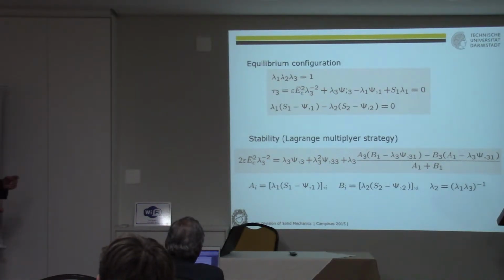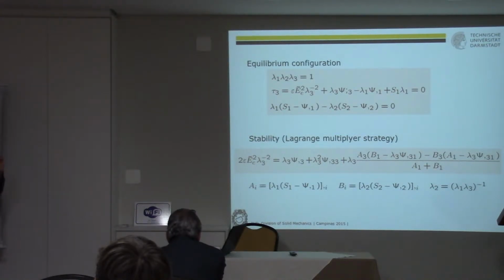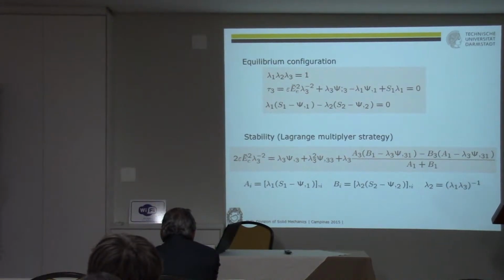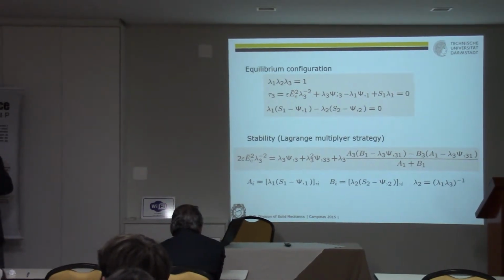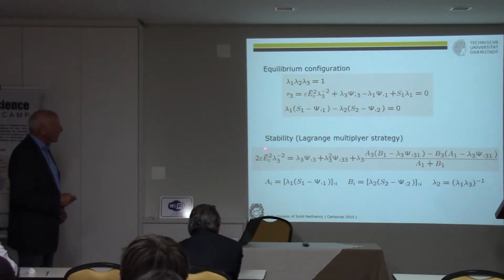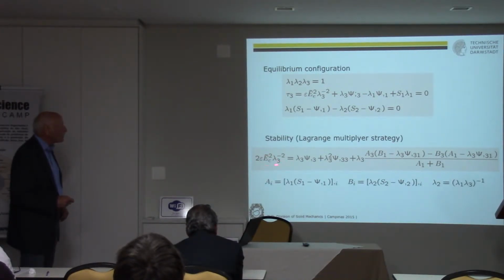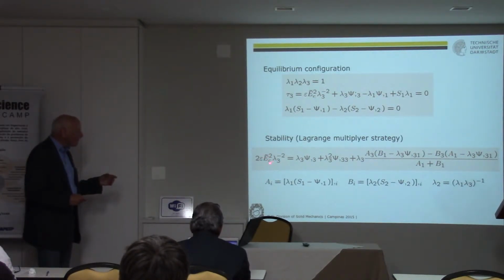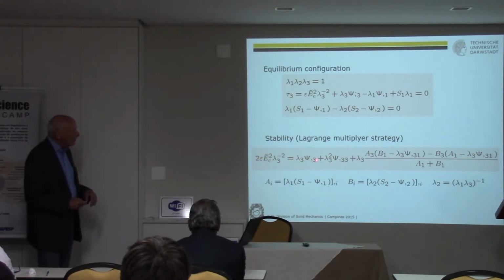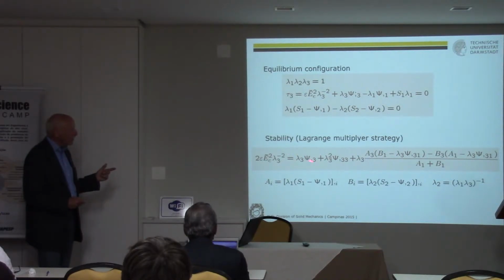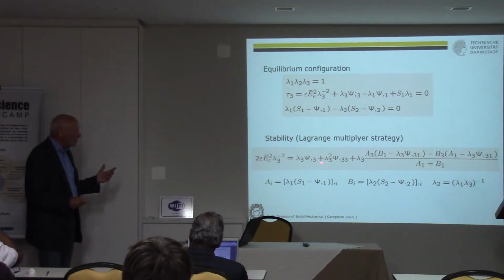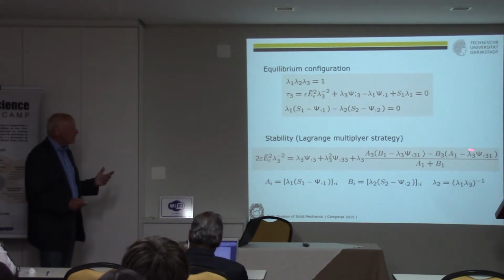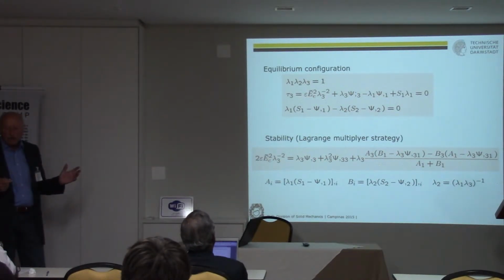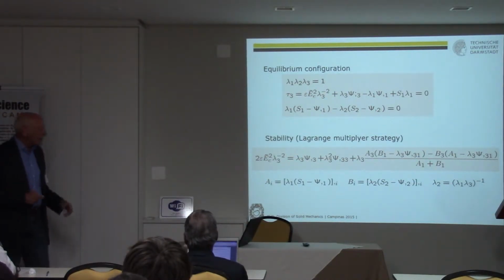Because in electrical engineering, they always had a problem if they apply an electric load, for instance, or a mechanical load, they got electric breakthrough, or really an instability. So we got a condition for stability, and it's given here, and what you see here is the necessary electric field to get instability. Here the lambdas appear, and this is for psi, the potential, which describes in some sort the behavior of the material, and this is a very general equation which is valid for all possible materials, if they have a potential.